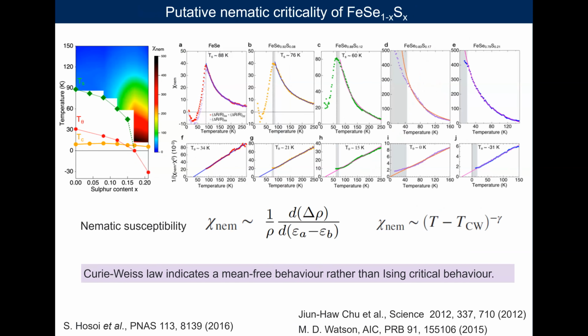The existence of the nematic critical point has been postulated also to occur in iron selenium sulfur based on this nematic susceptibility data. As I mentioned at the beginning, this type of technique is used to probe the presence of the nematic electronic phase, in which we look at the development of anisotropy in the presence of a very small amount of strain. And the Curie-Weiss-like behavior is used then to plot the intercept, so kind of the Curie-Weiss temperature. When the Curie-Weiss temperature, T theta, goes through 0, it has been suggested that that's the nematic critical point. So here it's very close to the phase transition between the nematic and the tetragonal phase.